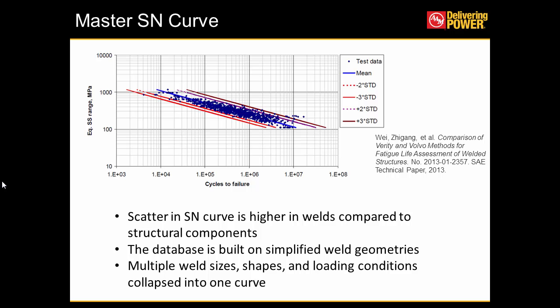Some other unique advantages of this process: we don't have to worry about the separate representation of the base material or heat affected zone and the weld material. Also, the yield strength is not a factor. Multiple tests were done on different grades of steel, up to even 1000 megapascal, and it was found that one curve is able to represent the entire case. And the tensile strength has very minimal effect. So for all those cases, we can use one curve, and this curve is this master SN curve.